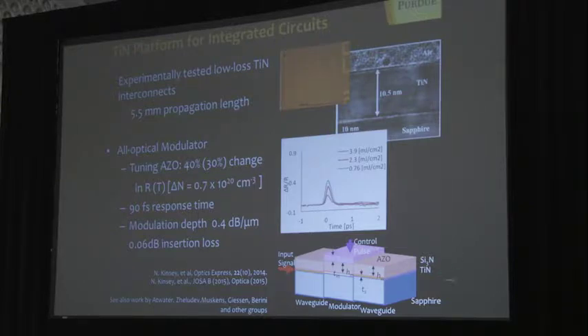If I put this aluminum-doped zinc oxide on top of this interconnect waveguide, of course the propagation properties of this waveguide depend on the cladding, which in this case is AZO. And with AZO, I could dramatically change optical properties, as I pointed out. Since I'm talking about 1.5 micron telecom, I could switch AZO almost from metallic to dielectric behavior, which means that propagation through this waveguide could be on or off, and I could do it in a very fast way.